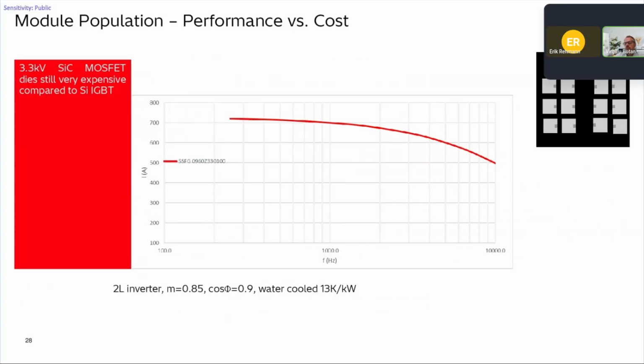Now, when it comes, of course, to performance, because we spent all this effort for silicon carbide because it promises very high performance. We see here the current output versus frequency for silicon carbide 3.3, which has what we call full population of the module. It means that on the ceramic substrate, we put as many chips as we can possibly fit. So we fill out the whole area. And the characteristic, of course, of the silicon carbide is that due to the low switching losses, the dropping of the output current at higher frequencies is much milder or lower than compared to silicon.